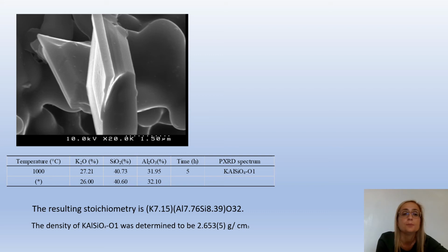This is a typical image of a KAlSiO4-O1 crystal from the sample at 5 hours, showing an average maximum length of crystals observed to be around 4 microns. The Si/Al ratio is in good agreement with the results of Stebbins et al., who obtained a similar ratio for a kalsilite synthesized starting from oxides. We report the resulting stoichiometry of the as-synthesized KAlSiO4-O1 together with the density value, which is in good agreement with the value obtained by Kremenović et al. 2013.